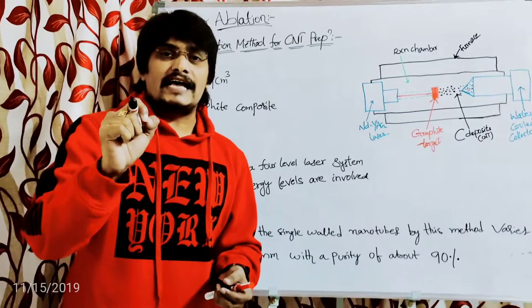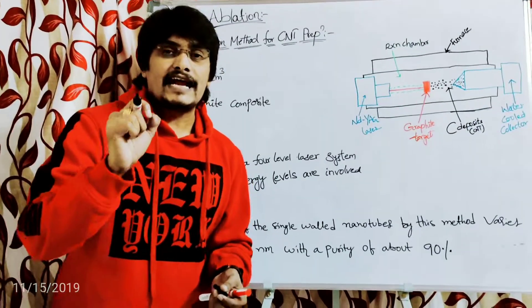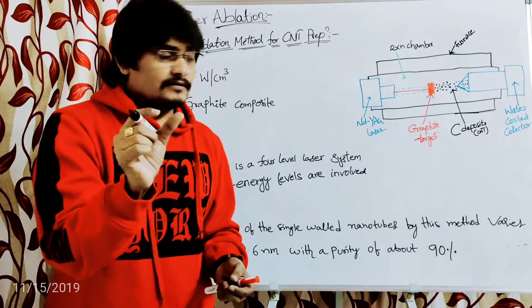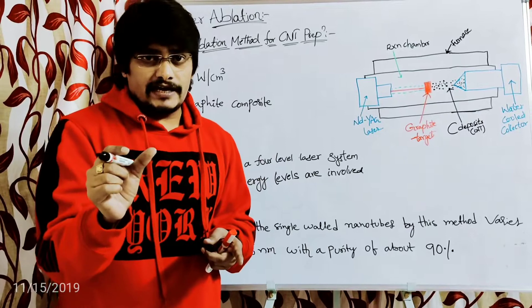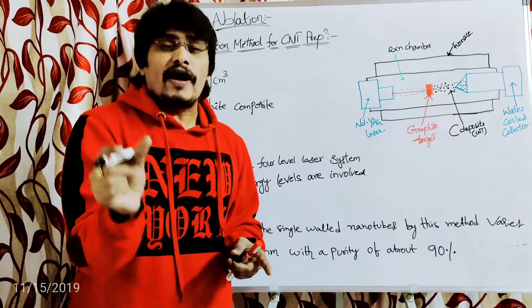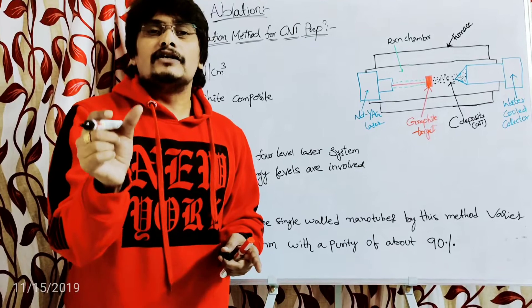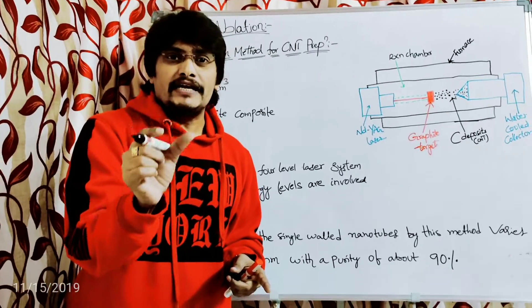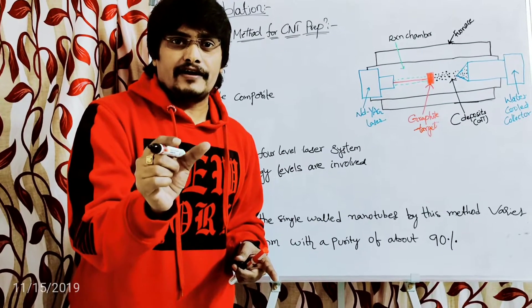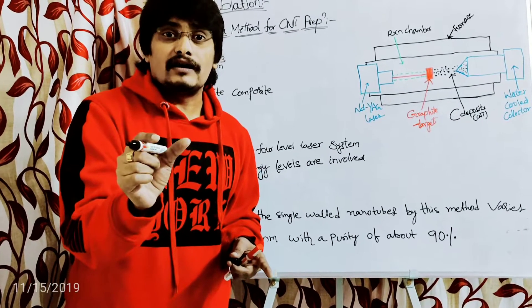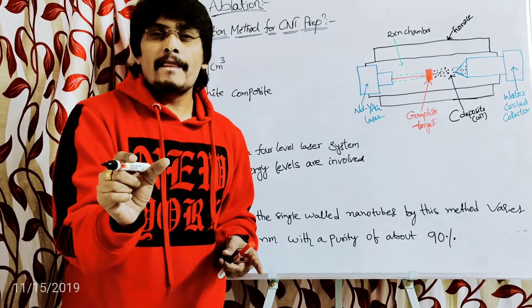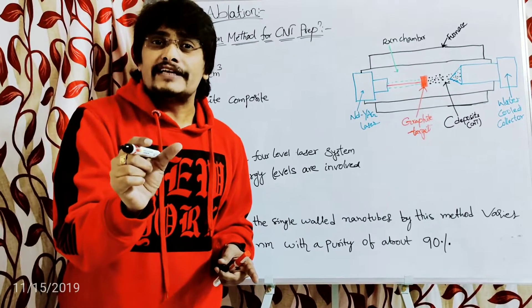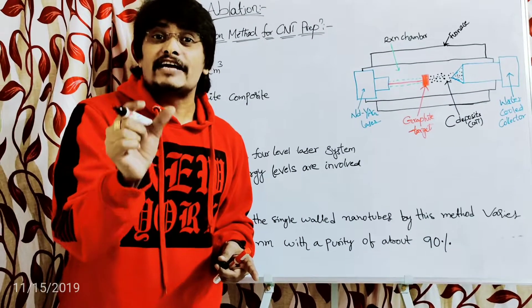In this graphite composite, we impregnate one percent of either cobalt or nickel metal, which acts as a catalyst. This graphite target comprising one percent cobalt or nickel is placed in a quartz furnace maintained at 1200 degrees centigrade under an argon atmosphere.